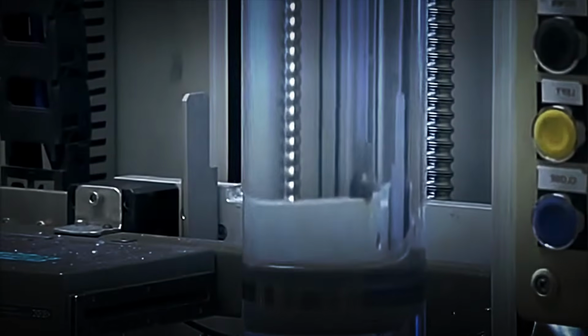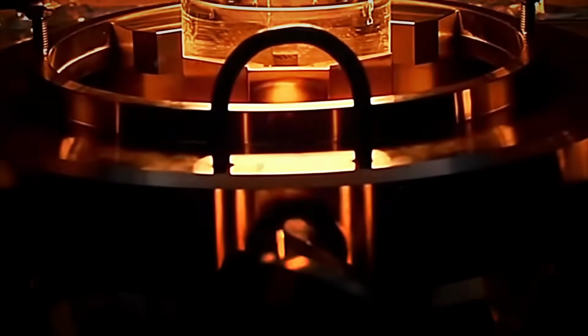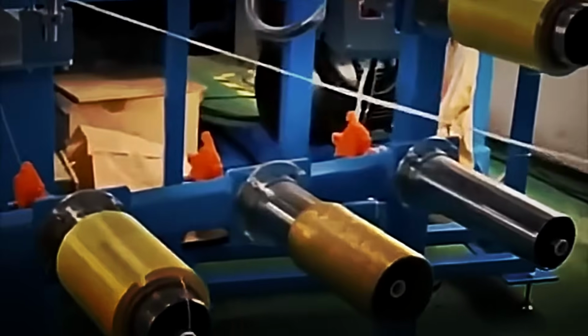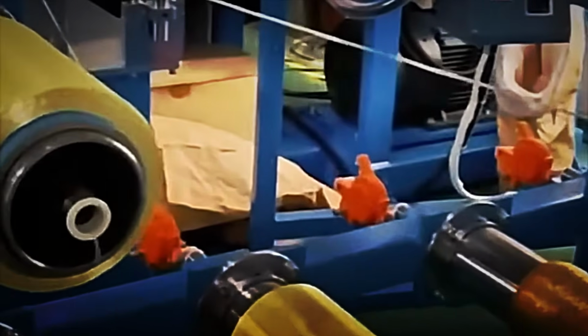Once the necessary layers have been deposited, the tube is heated again until the inner walls melt and seal, forming a solid cylinder. This cylinder is known as a preform. Each preform is examined using optical and mechanical inspections, and those exhibiting microscopic bubbles, cracks, or variations in composition that could cause signal loss are discarded. Only cylinders with complete transparency proceed to the next stage.